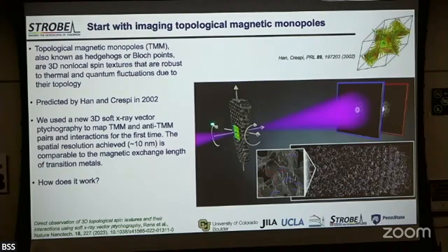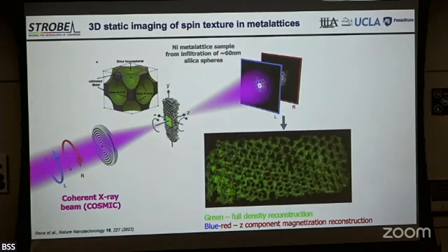And here, this is one example of where we use polarization structured light. We use either left or right circularly polarized X-rays. And for each one of those polarizations, we need to make a ptychography scan. Then to do the tomography, we have to do tomographic scans. And to get the full tomographic 3D spin texture, we need to do 3 tilt planes. So this was a lot of data.